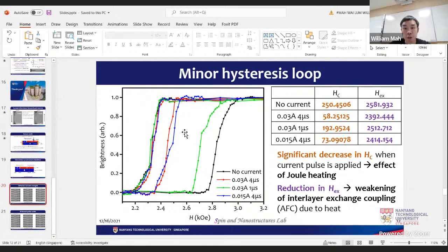Oh yeah, definitely. I varied the current strength as well as the current pulse width. This is the case that I showed you just now, 0.03 ampere. But if I reduce it to 0.02 and 0.01, especially 0.01, you see no difference. At 0.02 ampere, you see just a little bit of pushing, from here to here, it's pushed slightly. And also, if I vary my pulse width from 6 microseconds down to 3, down to 1, you also notice a less obvious integrate and leakage function.